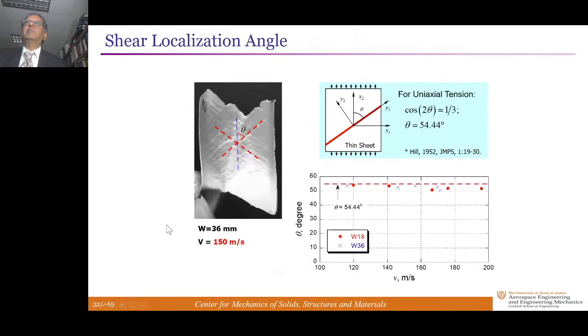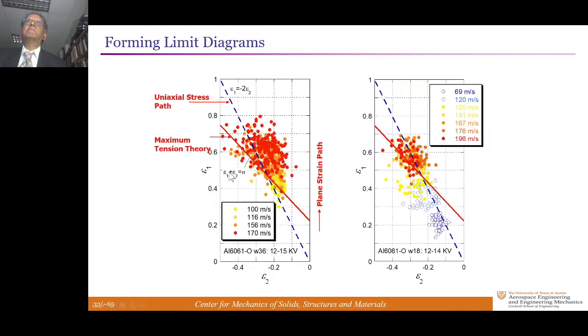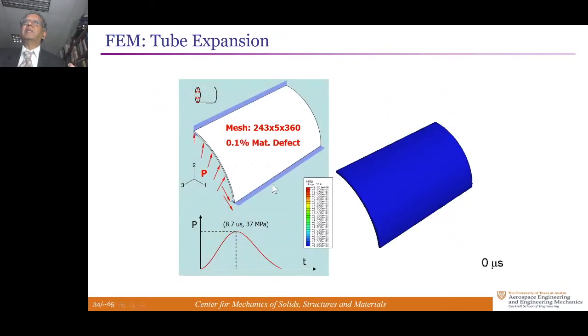I think I will skip these things. Again, post-mortem examination is important because it shows localization has occurred in multiple locations. They are of the sheet mode necking in this case. The angles are exactly what's predicted by Hill's quasi-static analysis for uniaxial tension. And so again, strain at onset is exactly what's predicted by quasi-static analysis. Strain rate effects in this particular material, this is a 6000 series aluminum alloy, don't seem to have a very strong role to play. You can construct dynamic forming limit diagrams from this, but I'll again skip that.